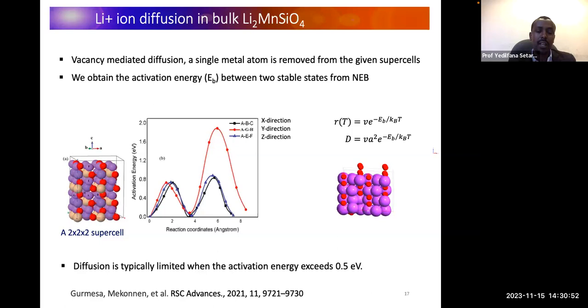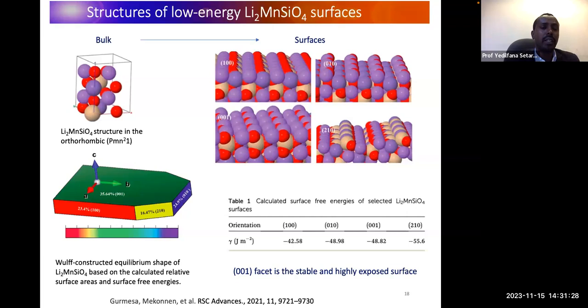We consider an acceptable or minimum barrier to be 0.5 or below. But unfortunately, in this case, all the diffusion activation energy barriers are above 0.5, right? So we need to implement some other strategies, as I mentioned earlier: either surface engineering, lattice strain, interface, or doping. So in our case, for this particular example, we use the surface engineering mechanism to improve the conductivity of the bulk lithium manganese silicate.